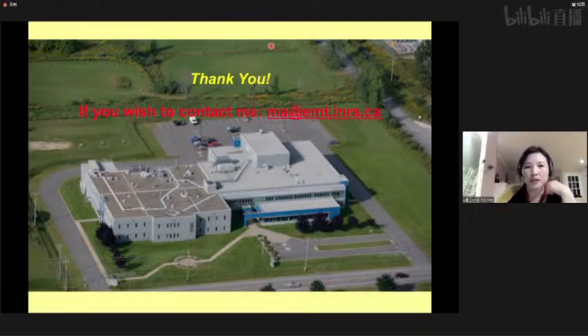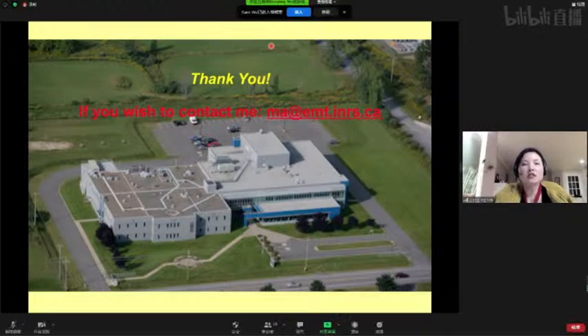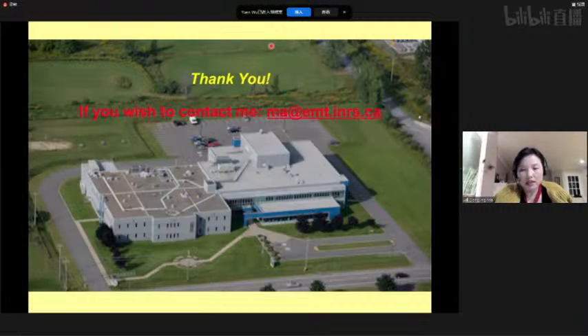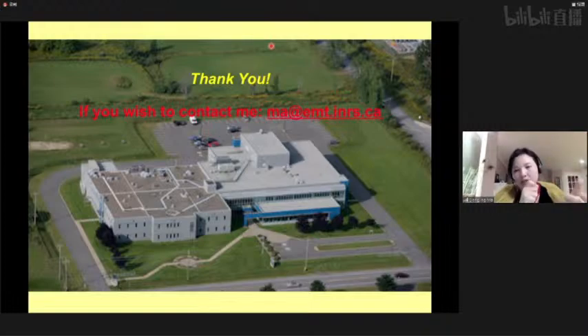Okay, let me quickly go to, I don't know why it looks frozen now. Okay, so actually the composition is slightly different. The top plate and the bottom nanoplate all contain carbon, nitrogen, cobalt. But what we did is plot the cobalt versus other elements ratio. We found that for the center part, the ratio is higher compared to the edge part. The edge part is composed of a bottom nanoplate, but the center part is composed of the top plate and the bottom plate together. Because the center part shows slightly higher cobalt concentration, we think there's a slight difference. The cobalt concentration seems higher in the top nanoplates.